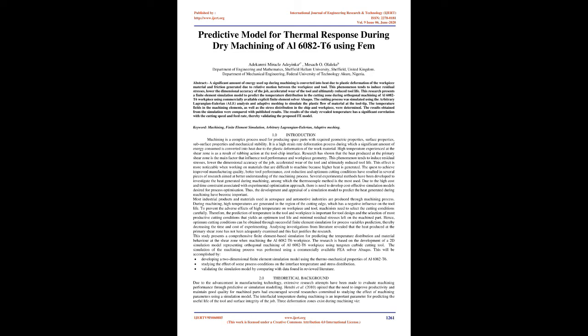The temperature fields in the machining elements, as well as the stress distribution in the chip and workpiece, were determined. The results obtained from the simulation were compared with published results. The results of the study revealed temperature has a significant correlation with the cutting speed and feed rate, thereby validating the proposed FEM model. Keywords: machining, finite element simulation, arbitrary Lagrangian Eulerian, adaptive meshing.